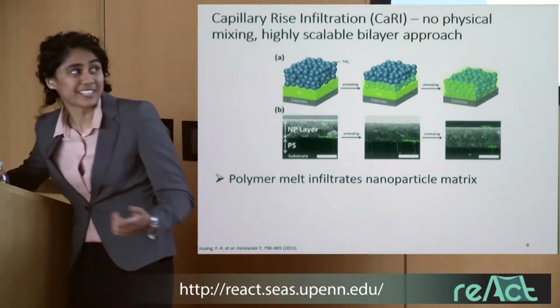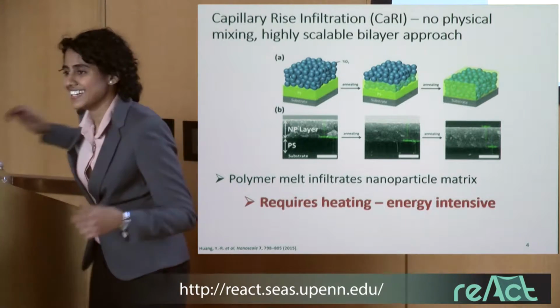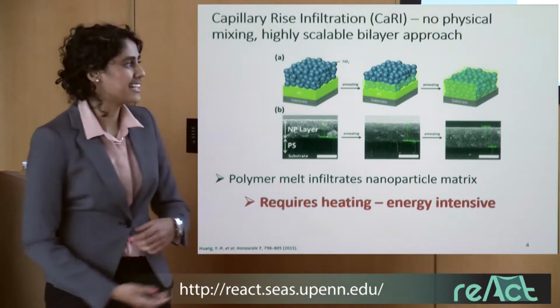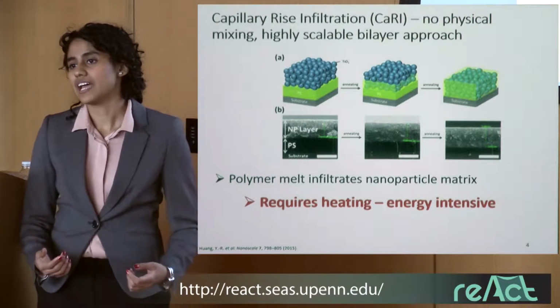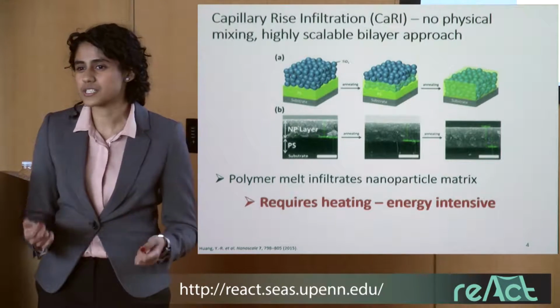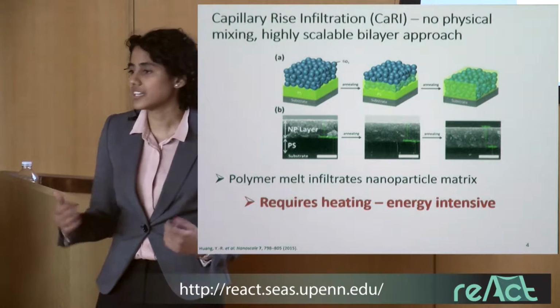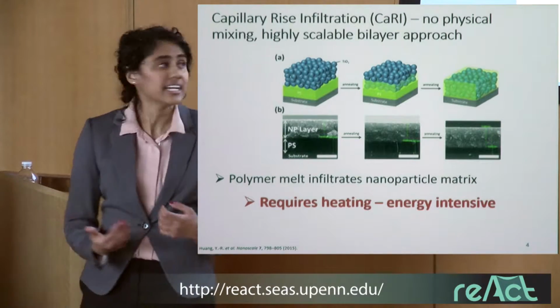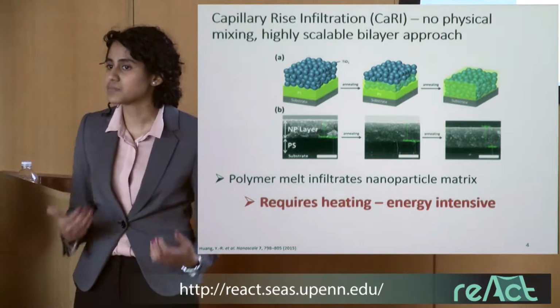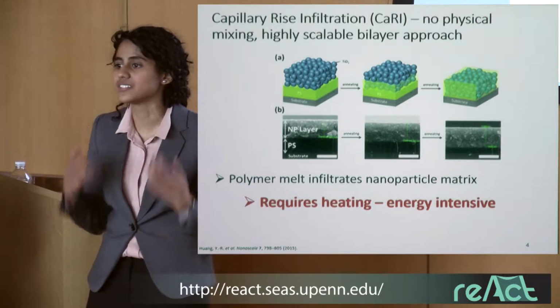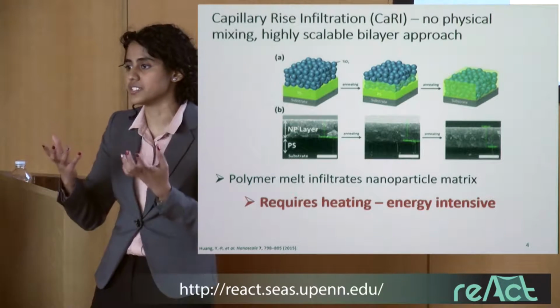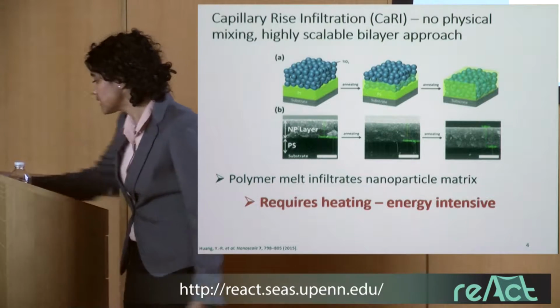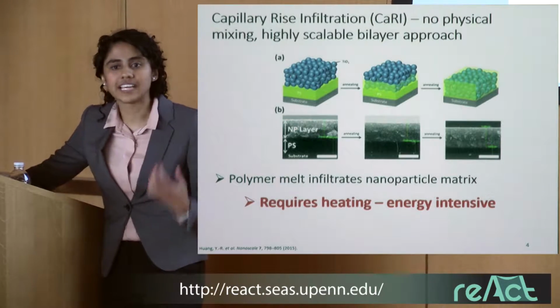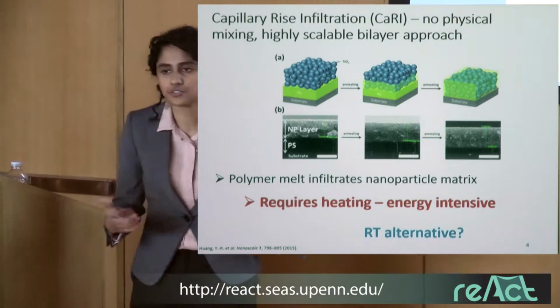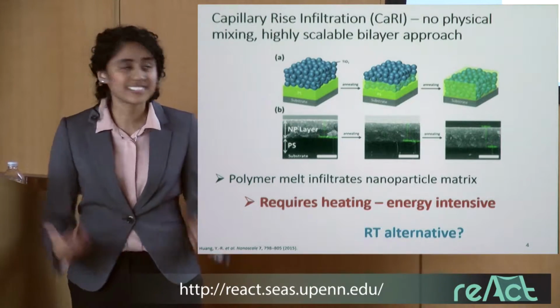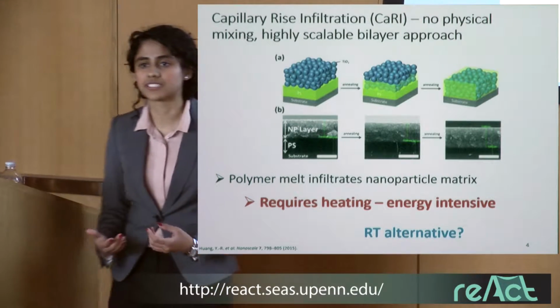However, this still requires heating, and it's still a little energy intensive. And conventional separation membrane polymers can have very high Tgs as they're very glassy. And this could mean that you have to heat them to quite high temperatures in order to get this softening effect, to drive them into these nanoparticle voids. So what we'd like, ideally, to reduce this energy cost is to have a room temperature alternative method that still circumvents the need for physical mixing.